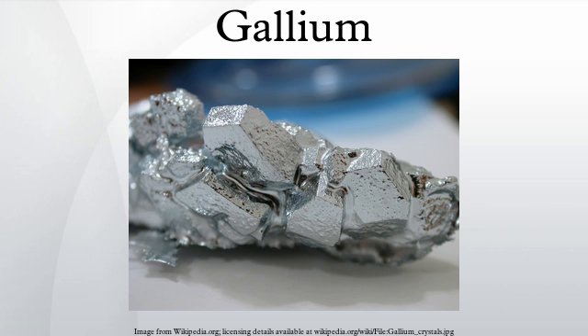Gallium attacks most other metals by diffusing into their metal lattice. Gallium, for example, diffuses into the grain boundaries of aluminium-zinc alloys or steel, making them very brittle. Gallium easily alloys with many metals, and is used in small quantities as a plutonium-gallium alloy in the plutonium cores of nuclear bombs, to help stabilize the plutonium crystal structure.